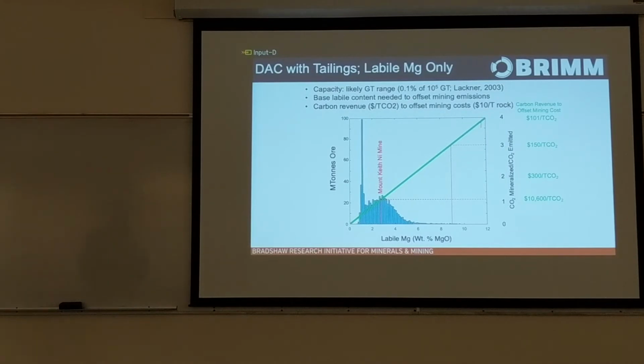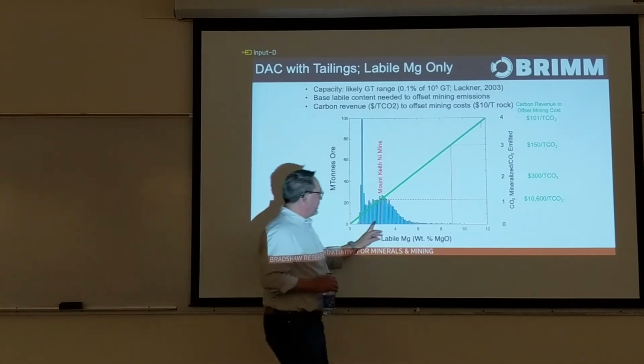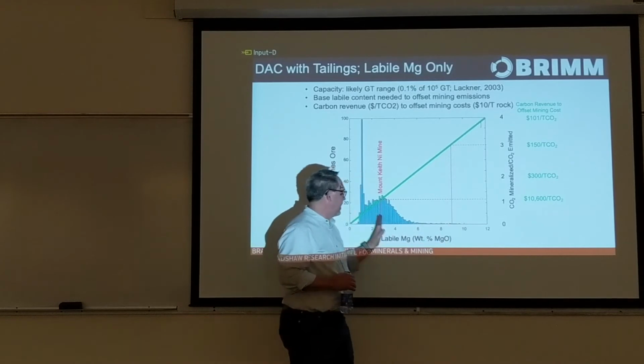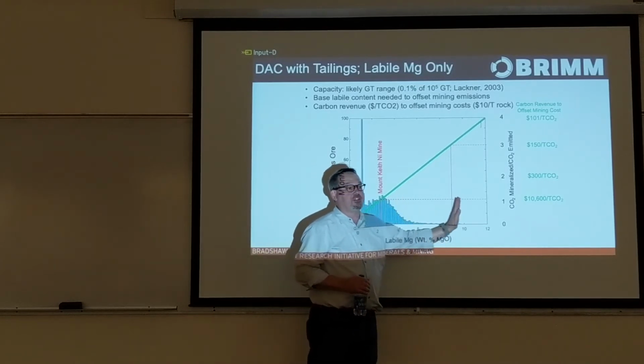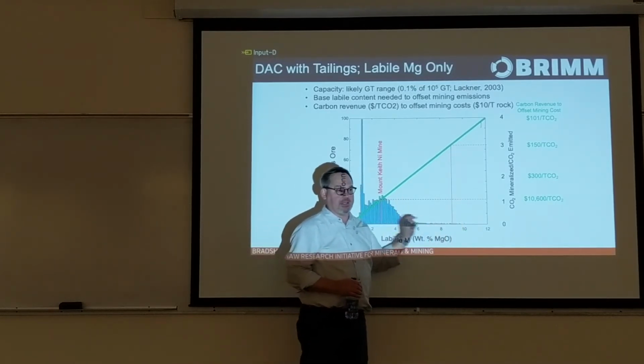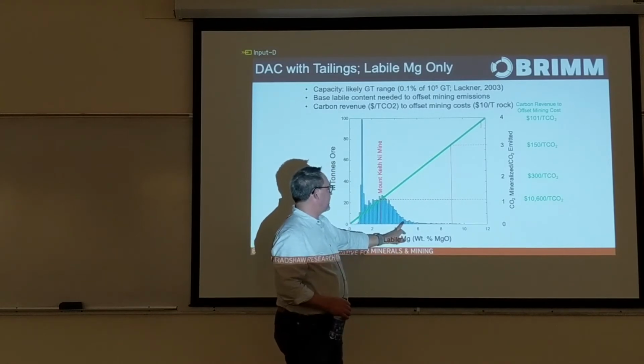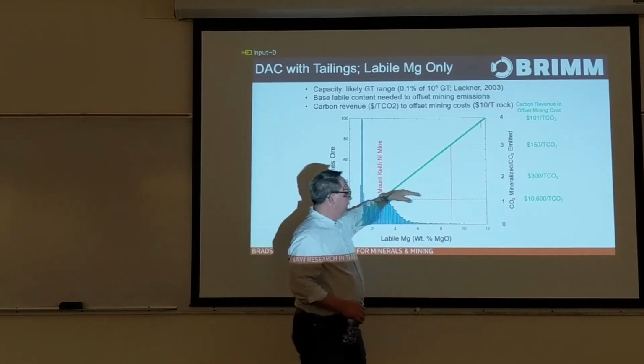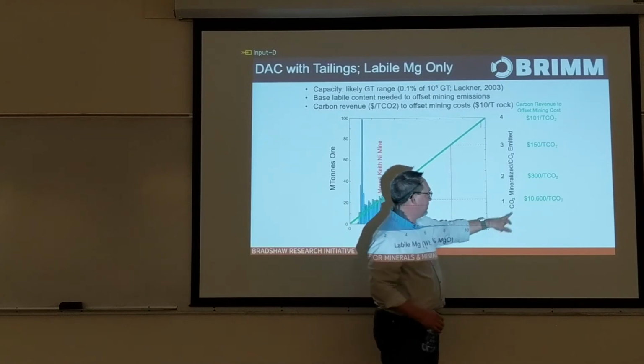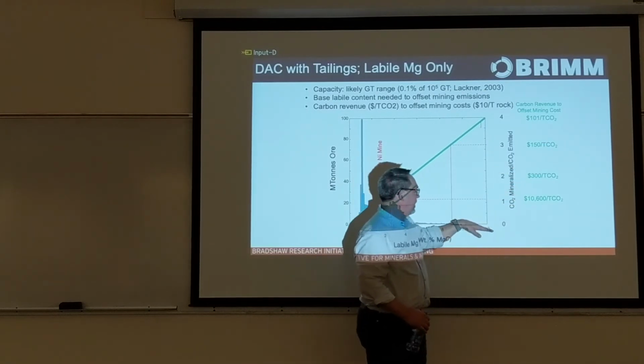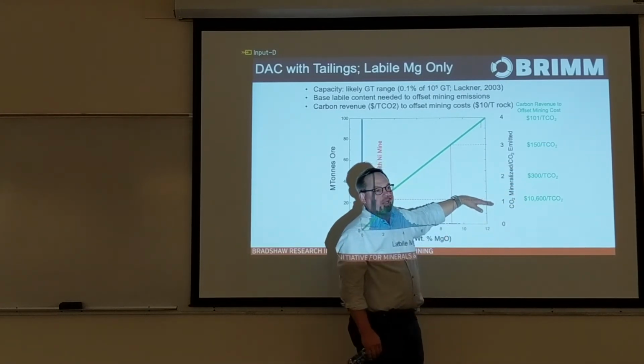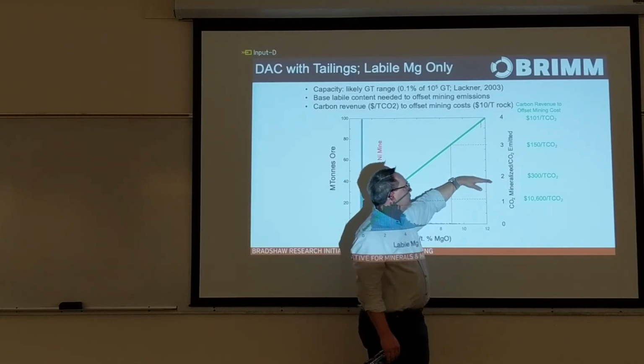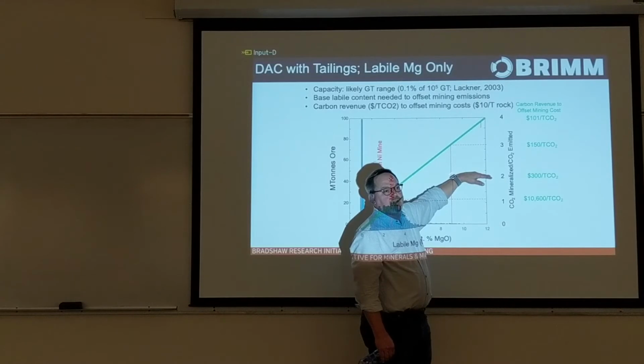If you imagine that instead of this being one deposit, you have individual deposits that have average contents that correspond to a certain labile magnesium content. You would take that average labile magnesium content, and if you read off the green line, this is now a ratio of CO2 mineralized to emitted. So the first time you get to 1, you've made the mine greenhouse gas neutral. If you double that, you've essentially sequestered as much CO2 as you emitted, made your mine CO2 neutral, and sequestered another equivalent amount of CO2 in the tailings.